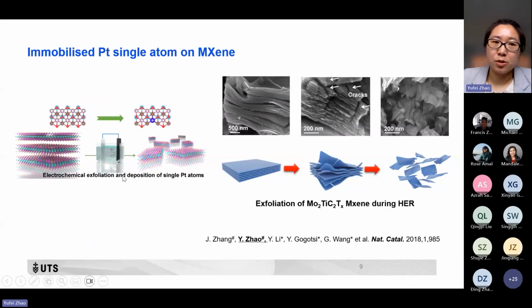For our experiment, we utilized this three-electrode system to prepare the single atom catalyst using MXene as a substrate. In the system, we use platinum foil as a counter electrode, and during the electrocatalytic process, platinum ions can be etched out from the platinum foil and dissolve into the electrolyte. The dissolved platinum ions can be captured by the MXene on the working electrode to form the single atom catalyst. Besides forming the single atom catalyst, during this HER process, we found that the morphology has changed. The SEM image and schematic illustration show that during the electrochemical process, the loosely packed MXene, obtained by etching the A element from the MAX phase, has been exfoliated into two-dimensional nanosheets. That means during this electrochemical process, the electrochemical exfoliation and the deposition of single Pt atoms occurred at the same time.